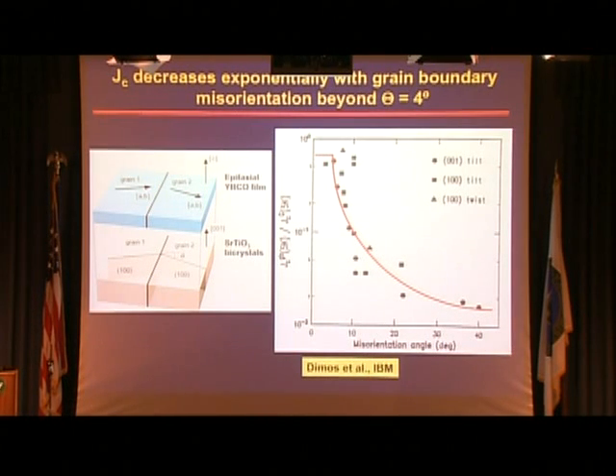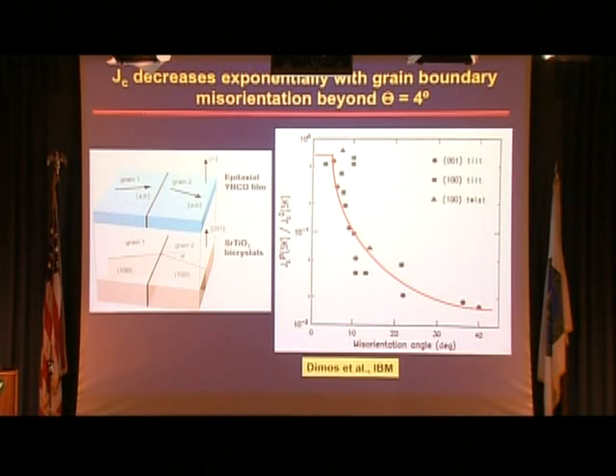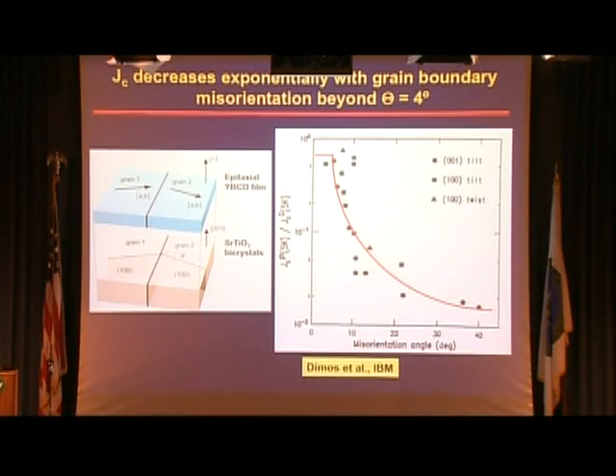So, an elegant experiment was done at IBM where they said, let's take a crystal and create an interface artificially by misorienting the two sides of an interface in a strontium titanate bicrystal, and then deposit a superconducting film so that the atomic configuration of that film adopted the same atomic configuration as on the surface on which these were being deposited, and then pass a current through the interface thus created within the superconductor. So you plot the amount of current that you're passing through this interface versus the amount of current you can carry within a grain on the y-axis as a function of the misorientation angle at this interface, independent of what the relative type of this interface was. And you found that in all cases above 5 degrees, there was an exponential drop in the amount of current that could be transmitted across the interface.